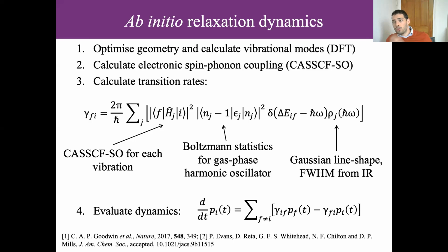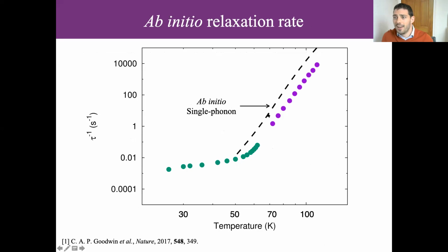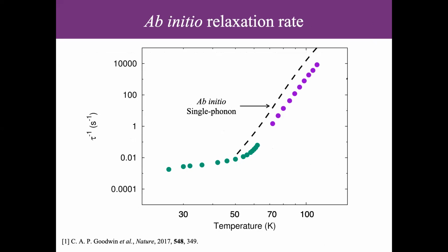Oh yeah. So to just follow on from what I was about to say before, why it's taking so long is that we're also looking at the dispersion of the phonon modes in reciprocal space, with phonon wave vector. So essentially, for those of you who don't know solid state phonons too well, I assume other people are still around listening, what you have of course is phonon modes that do distortions in unit cells that are next to each other, but then you could have those distortions moving in counter directions, right, with different unit cells in different vicinities. And those are different wave vectors of a given phonon mode.